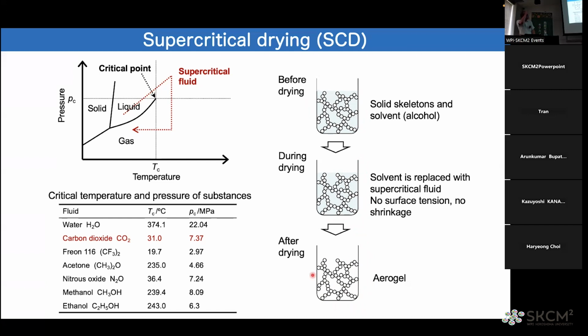So as I said, this process should be avoided because you need a high pressure and a special apparatus for drying. But I can also say this is a very efficient process because the drying finishes in not more than 10 hours, like a few hours. In a few hours, you can finish the drying. And this is a very time efficient process. So sometimes supercritical drying may be better than the ambient pressure drying, as I showed you later. Ambient pressure drying takes a little bit longer.